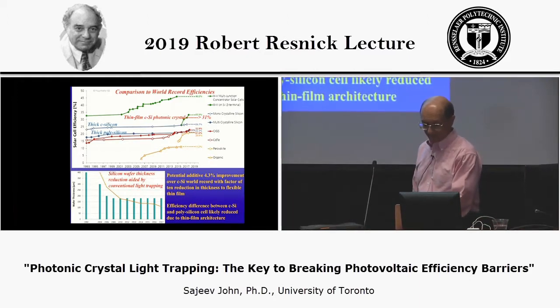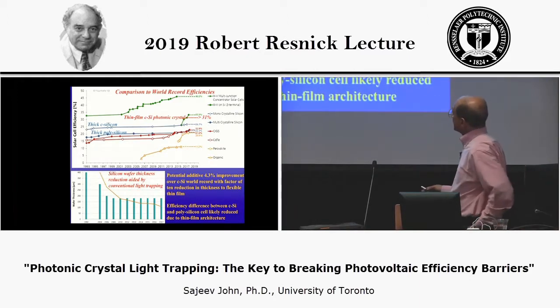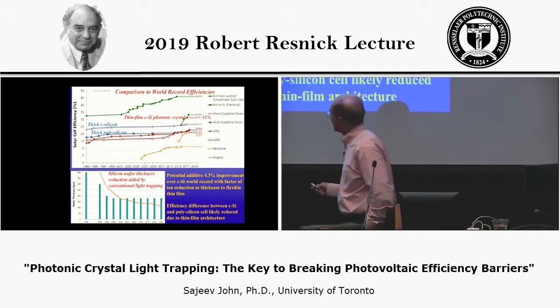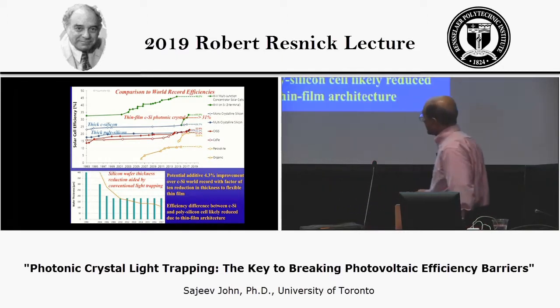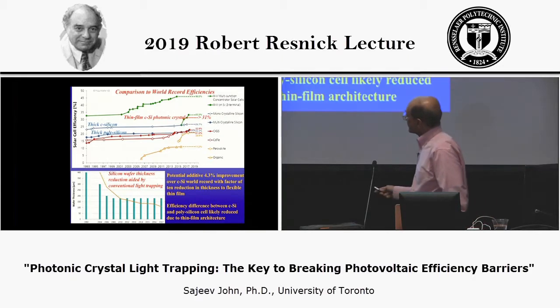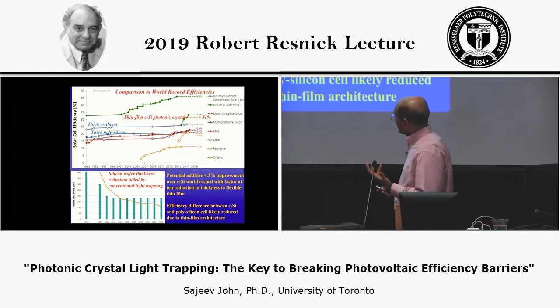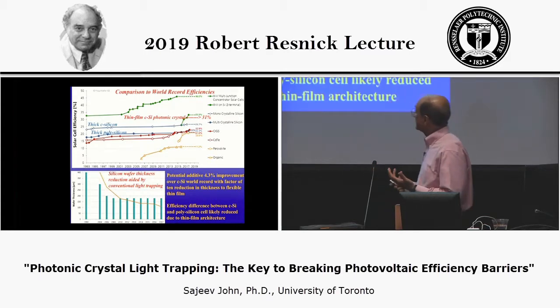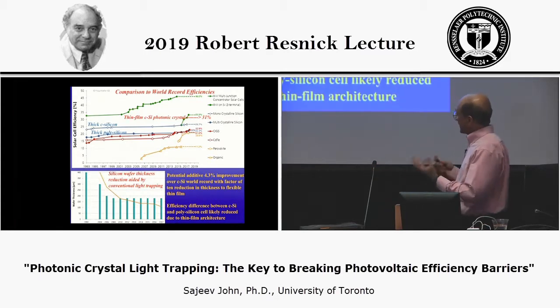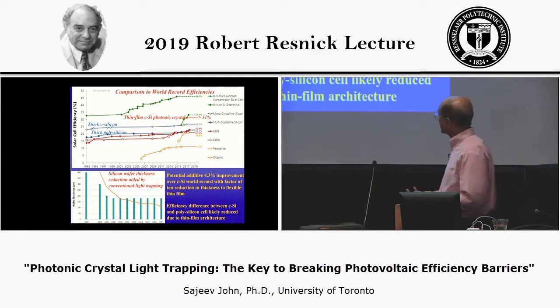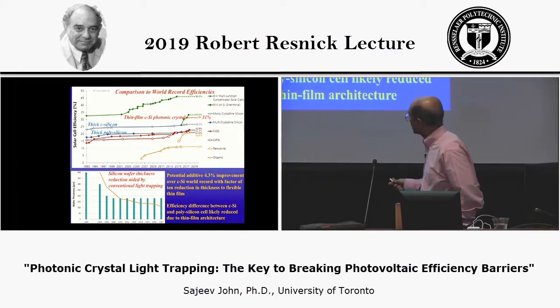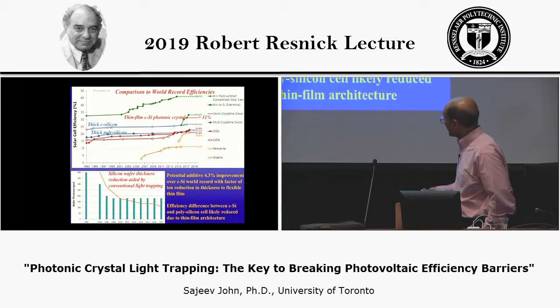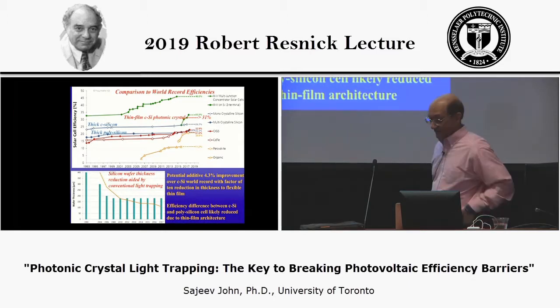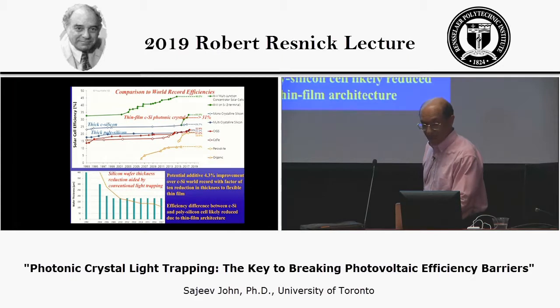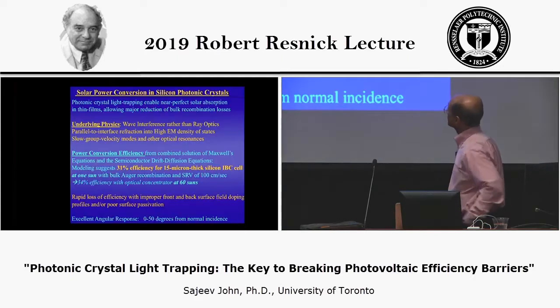And here's how the thickness of silicon solar cells has changed over the decades, starting from over 400 microns. As light trapping has been introduced, they brought it down to maybe close to 200 microns, but that is more statistical ray trapping. With wave interference-based light trapping, we should be able to achieve even higher efficiencies by going to the thin film regime, which is quite unexpected, actually.